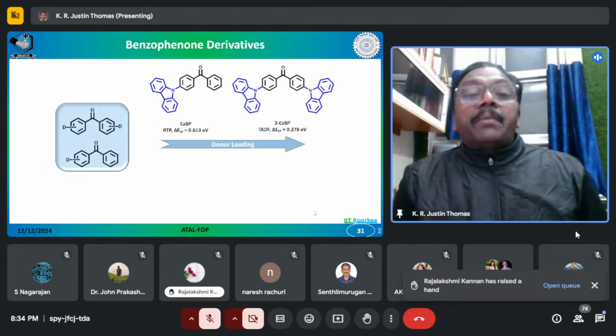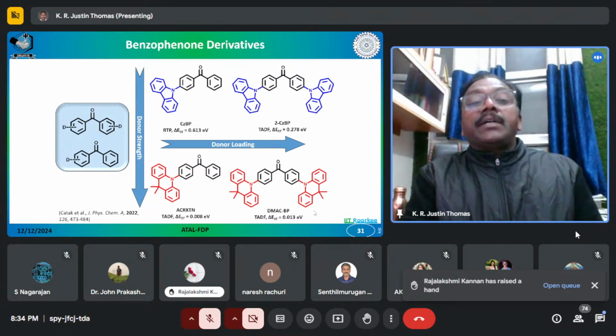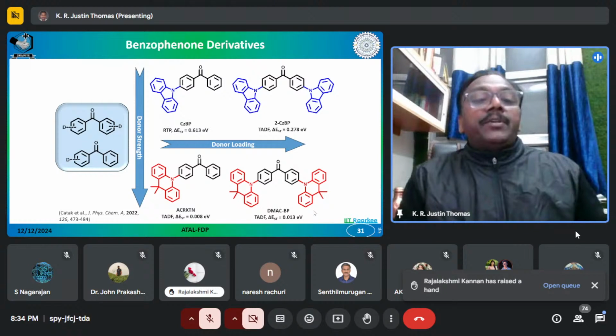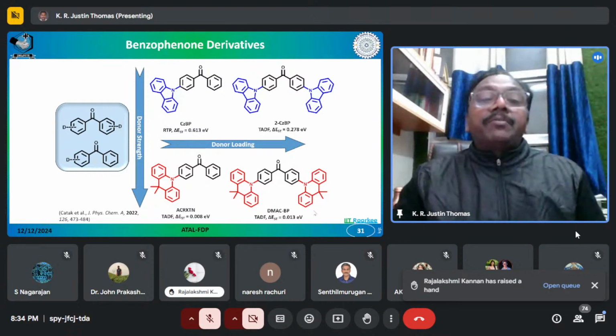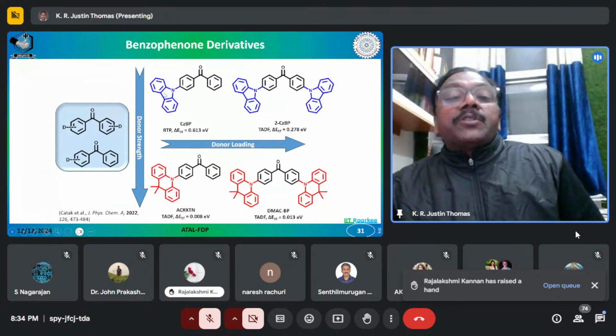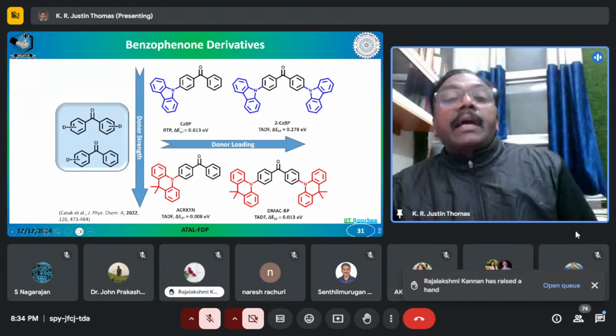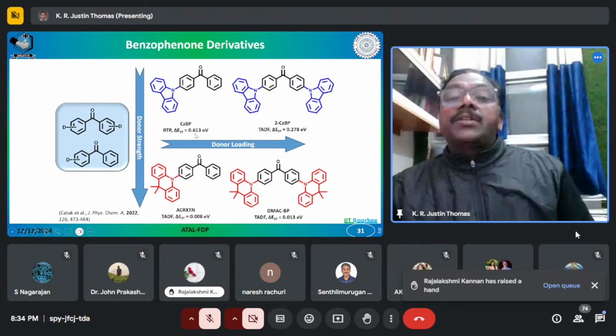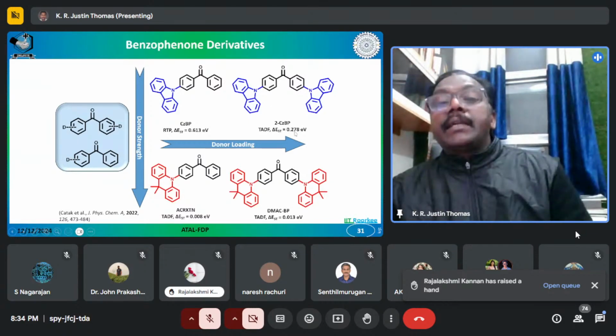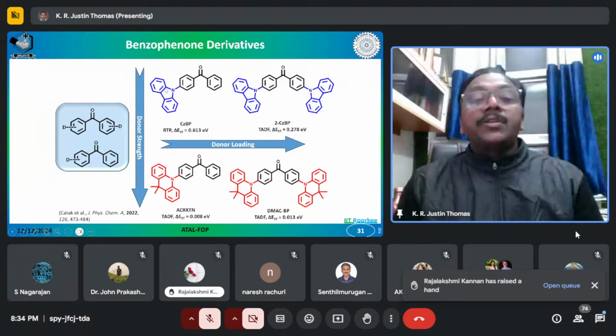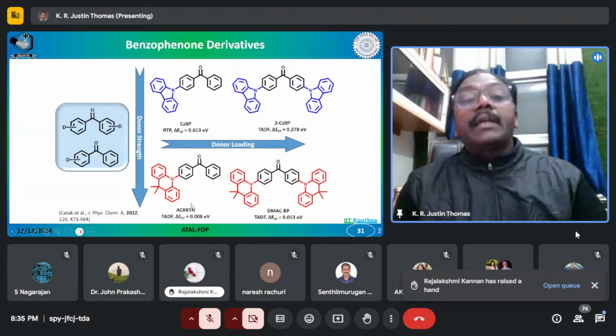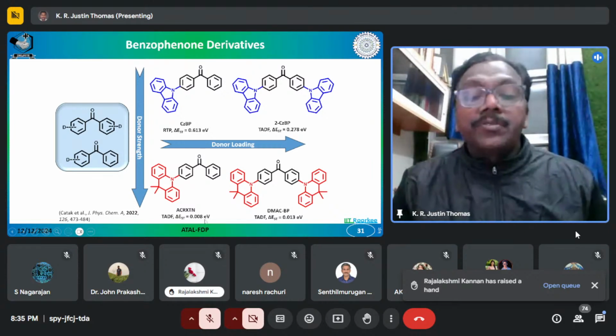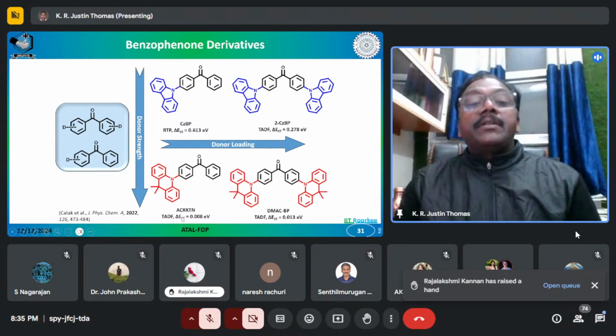And let me give examples to illustrate my point, why the benzophenone molecules are either fluorescent or sometimes even TADF, but it's not generally a particular class. If you look at here, when you have only one carbazole on the benzophenone, it is a room temperature phosphorescent material having a delta EST much higher than 0.5 electron volt. When you increase the number of carbazoles on the benzophenone, that is the donor loading, you find the delta EST is decreasing from 0.6 to 0.3. That makes the molecule TADF in nature. Alternatively, you can also change the weak carbazole donor to a strong acridine donor. Thereby, you can have a drastic reduction in the delta EST to almost 0.0.